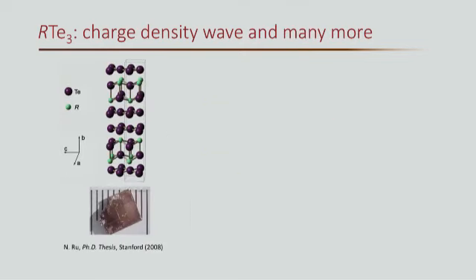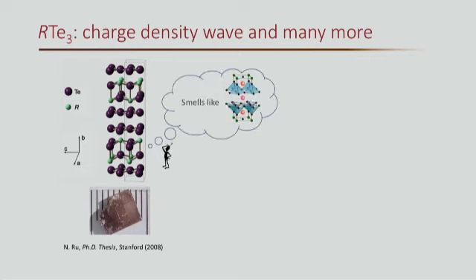Here, I just want to briefly show the crystal structure. The material itself is also highly two-dimensional. It basically consists of two tellurium square lattices, which make up the Fermi surface, and which are sandwiched by the two rare earth tellurium slabs, which act as a charge reservoir. If you are familiar with cuprates, you can make some analogies here, where we have copper oxide planes, which give rise to the Fermi surface, sandwiched by the two charge reservoir layers from a variety of different cuprates. And also, they are both square-like.